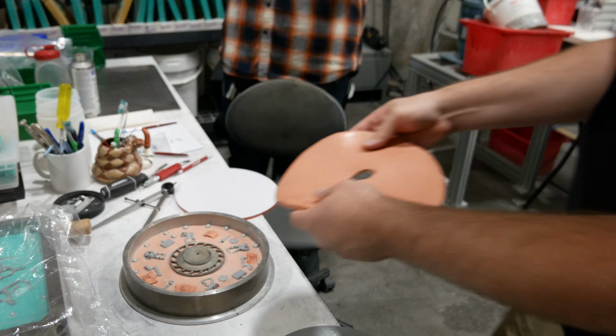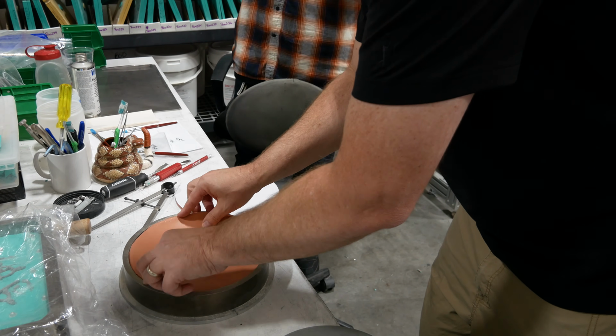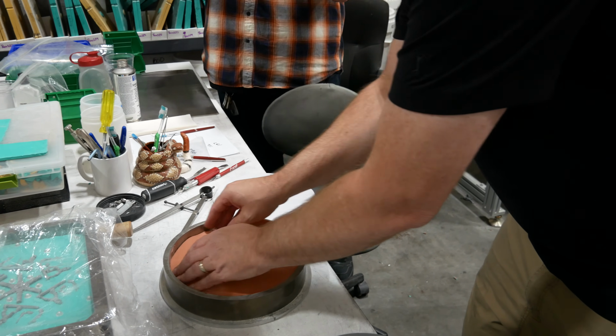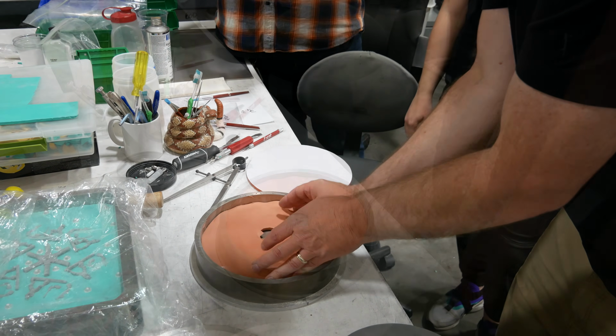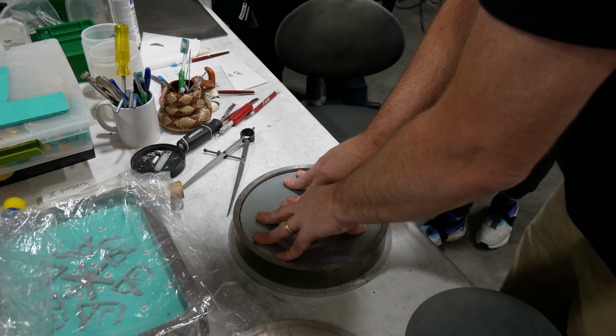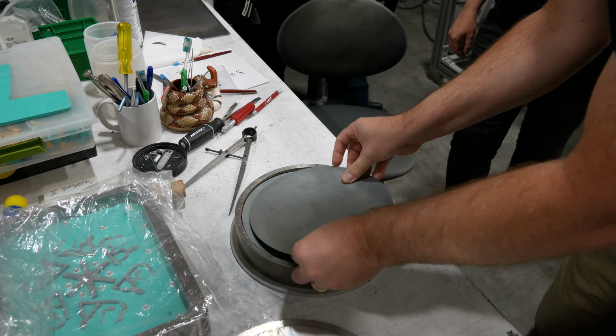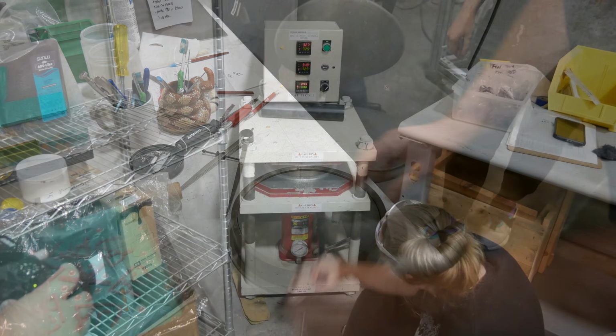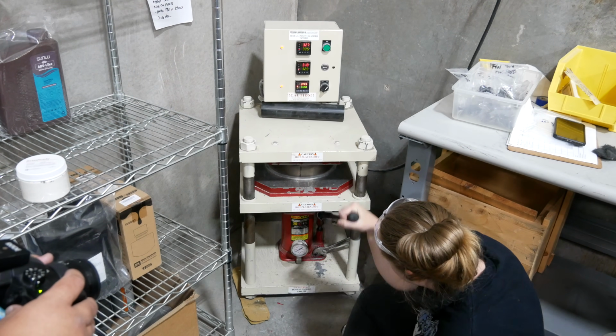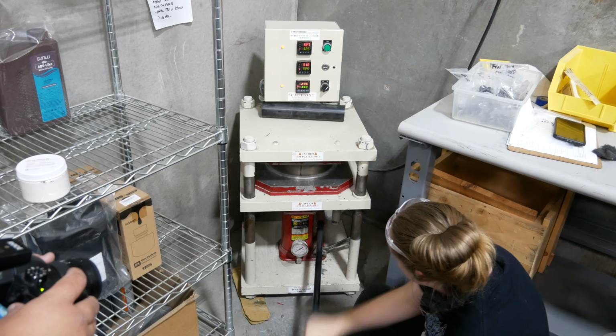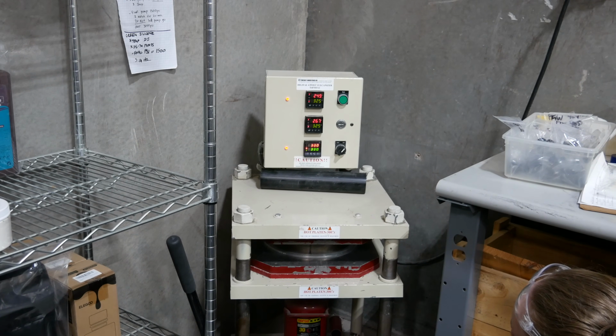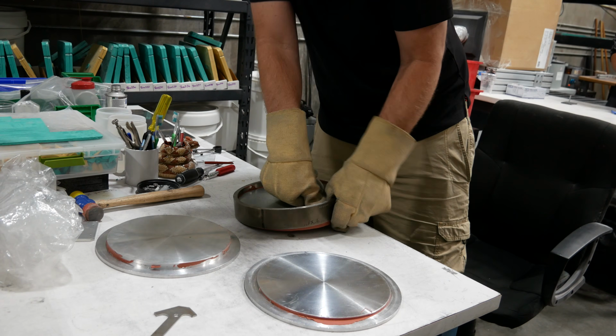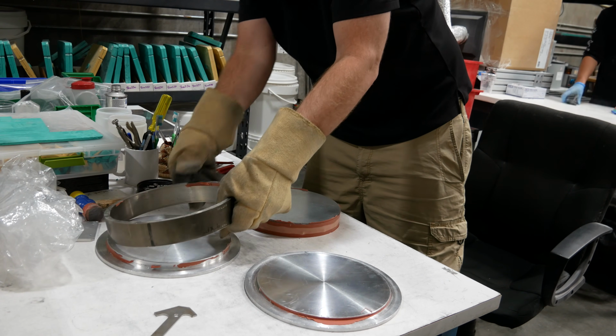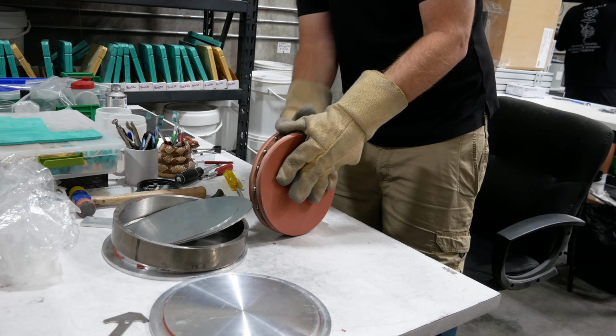A second fresh round of soft silicone is placed on top of everything. This will become the other half of the mold. A steel cap is placed on top, and this layer cake of nascent silicone is taken to be vulcanized. Heat and pressure are applied to the mold. This is the vulcanization process, and it causes the shapes to become permanent. After a few hours, the silicone has become much harder, and it will retain the details of the imprints.